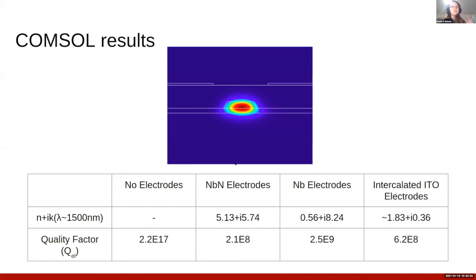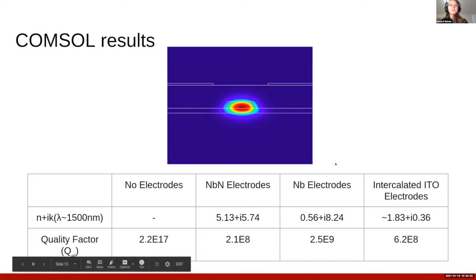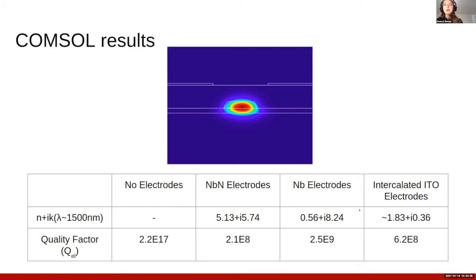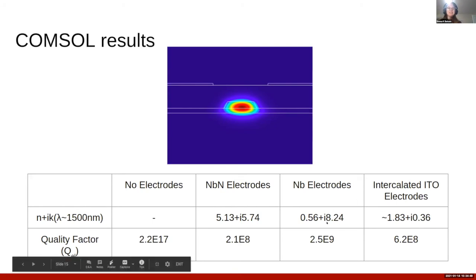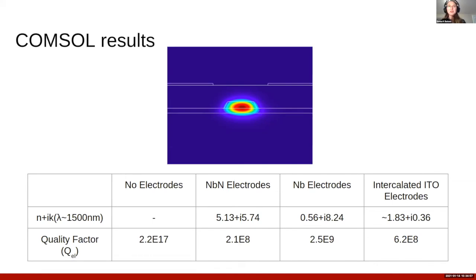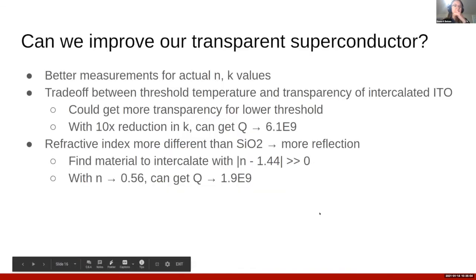When we do this, we see we have a super high quality factor when there are no electrodes to take in this optical absorption. And then we can look at the effect of using different materials for the electrodes. Our intercalated ITO electrodes, we estimate, would have a higher quality factor than niobium nitride, but actually a lower quality factor than just niobium. So what's up with that? Well, we can see that the niobium electrodes have a refractive index that's really different from that of silicon. So even though it has a pretty high extinction coefficient, a lot of the optical light is actually getting reflected, is my guess.